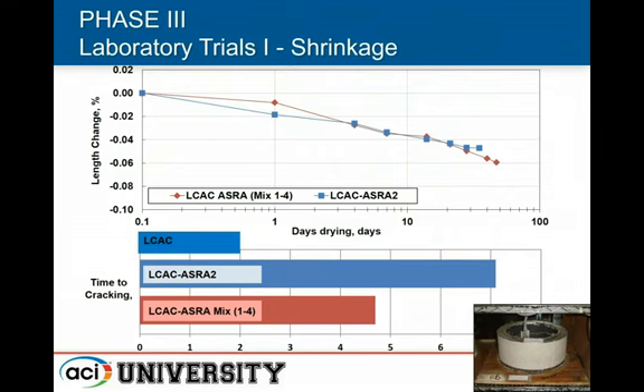This is a test that allows us to cast a concrete donut around a steel pipe for restraint. And as the steel pipe pushes back on the concrete as it tries to shrink, you ultimately develop tensile stresses, and you will typically see cracking in most concretes. If this cracking happens within the first week or so, we consider this to be a potential risk. In particular with patching materials, we want the cracking to happen sometime after the first week after the sample has been cast.